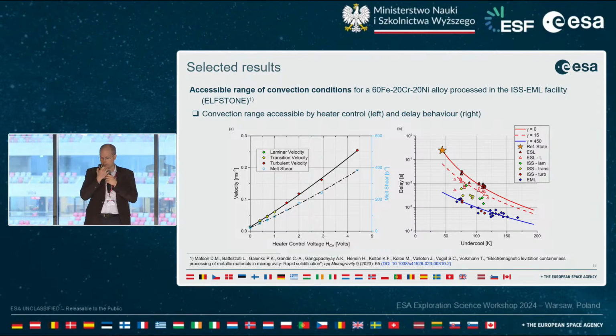On the right-hand side, you see the second parameter, the so-called delay time. In these systems there is metastable and stable growth. First metastable growth, and you can look at the delay time between metastable crystal growth in this sample and the follow-up of the stable phase growing afterwards. This is shown on the right-hand side. And again, for a particular undercooling, this is impacted by fluid flow. So you have a difference in delay time between the different experiments shown here.